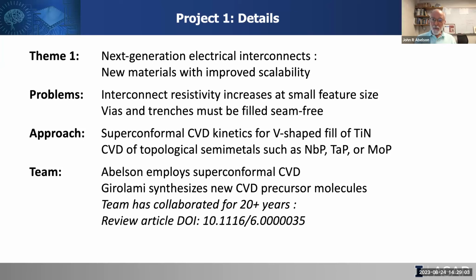The interesting thing about chemical vapor deposition, in addition to having pretty good growth rates, is that you can use unique kinetic features such that the growth is actually faster at the bottom than the top. So as growth proceeds, the bottom actually forms a V shape, and with continued growth, the V goes up and out of the feature. I'm demonstrating this with my hands. Sorry, it isn't on the slide. If you're interested in what Greg and I have developed, there on the bottom is a comprehensive review article that lists all kinds of things we've done. By the way, it also includes area selective deposition, enhancement of nucleation for super smoothness, and several theoretical formalisms to predict when you get conformal or superconformal regimes as a function of the precursor kinetics. Next, please.